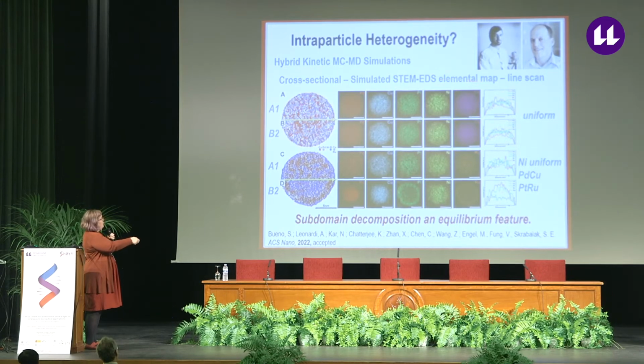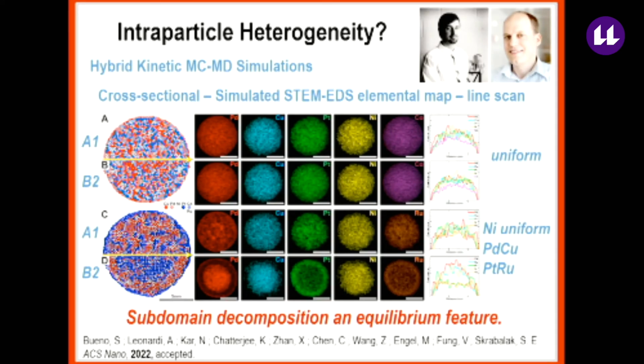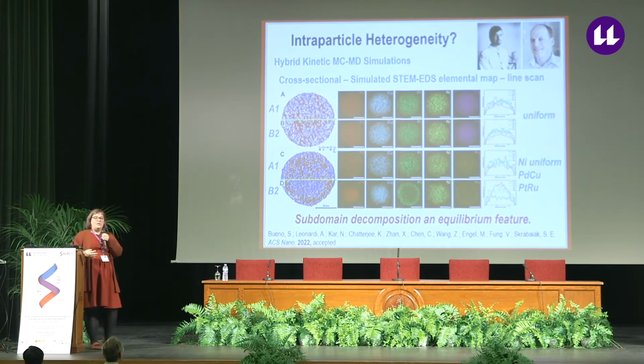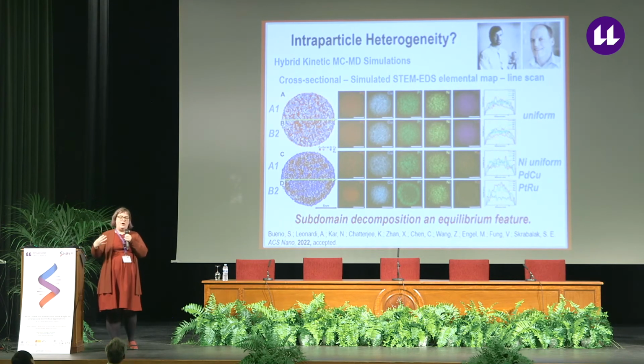And then that translates into the elemental maps shown here. So it matches quite well with our experimental observations. But on the bottom, you'll notice that there are some largely blue domains or red domains. And this is evidence of segregation of the different components. And this was present whether we started with an intermetallic palladium copper core or a random alloy palladium copper. Just the distribution of these patches was different. Here it's more of a core shell architecture, where in this case you have sort of little islands of this. So the bottom here is like our system that I reported, and you see this intraparticle heterogeneity. So what that's suggesting is that this intraparticle heterogeneity is an equilibrium feature of this specific composition.